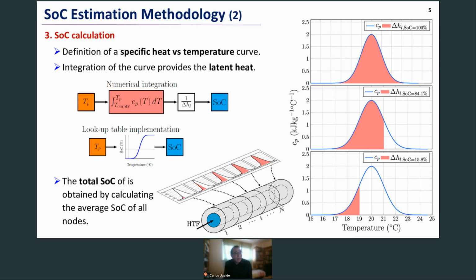The latent heat value is employed to calculate the state of charge, as this is the energy per unit of mass that produces the phase change. So for a hypothetical PCM with a melting temperature of 20 degrees, the graphs at the right-hand side show the state of charge for 3 different temperatures.